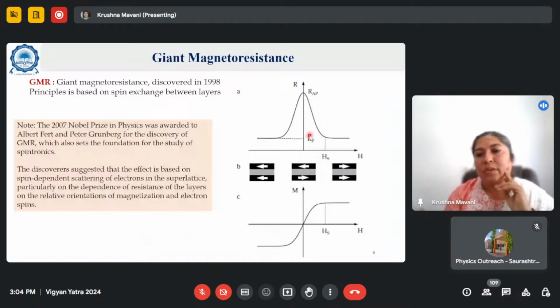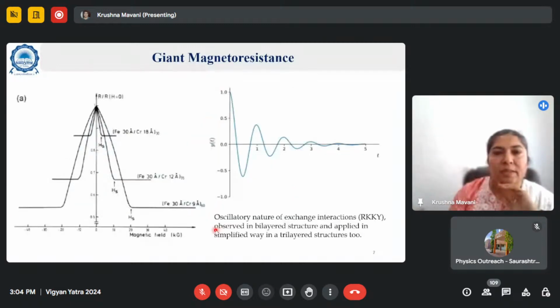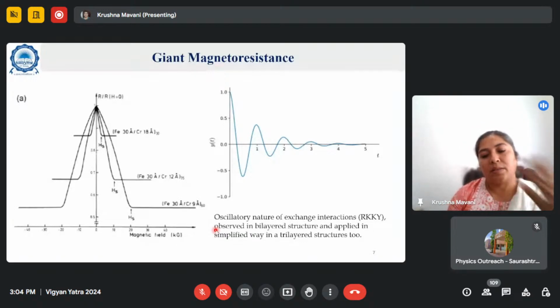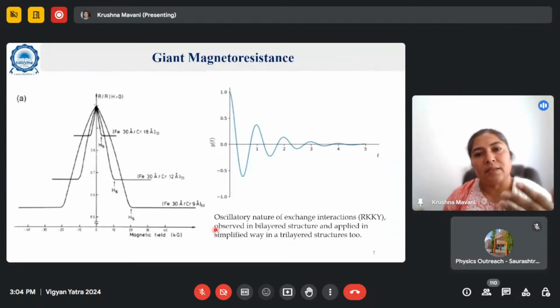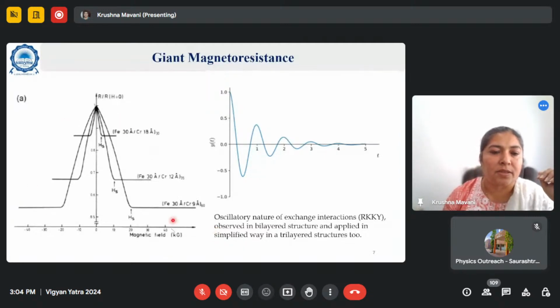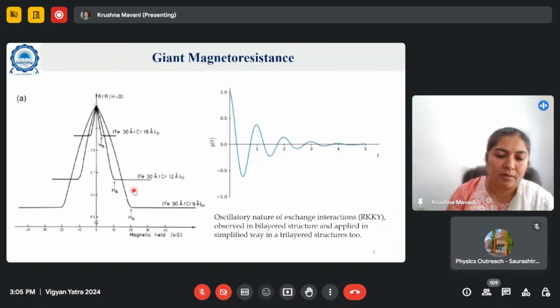So these vary the resistance, and it is called magneto-resistance, because on application of magnetic field, as the spins align parallelly, the resistance reduces drastically. This is the first discovery made in giant magneto-resistance multilayer of iron and chromium.